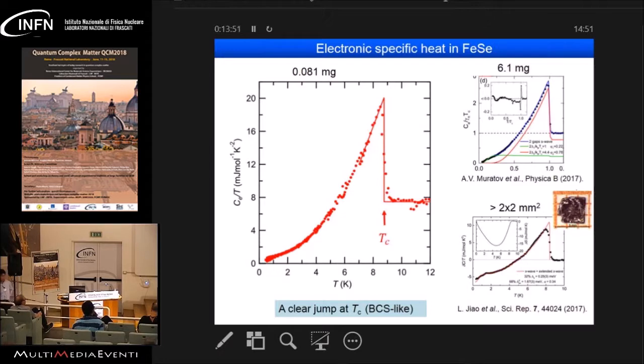So this is an example for iron selenide. We use very small single crystals because we want to use very pure single crystals. This sample is about 81 micrograms, which we can compare with the previous measurements, which used much larger single crystals. And as you can see, our data shows very consistent results with previous ones, and it shows a clear jump, right? So we can say that this is a typical BCS type temperature dependence of specific heat, right? Even though we have a situation where delta over EF is close to unity. So what's this, right? That's the question.